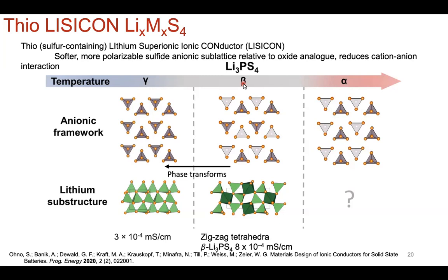High pressure, yes. There are also really cool ways of accessing metastable phases: instead of rapidly decreasing your temperature, you could rapidly increase your temperature. There are a number of ways to do that. There's flash sintering type of reaction. If you start off with powder precursors, you can flash sinter into one composition for your final product. You could think about microwave type technologies, which the ceramic community has also talked and thought a lot about for the last few decades. So you could really utilize different ceramics type synthetic strategies to access all these high temperature, high energy phases.